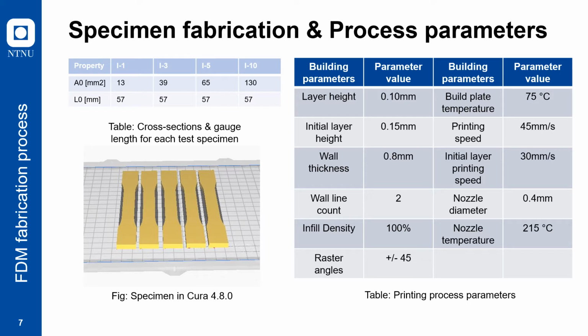Okay, so these are the fabrication parameters and the process parameters here. As I mentioned earlier, we have 4 different thicknesses for the specimen, and these are the cross-sectional area and the gauge length for each specimen. And these are the process parameters we have used to fabricate those specimens. We have made some trials and errors to be able to fabricate those, with 100% infill density and a relatively smaller layer height of 0.1 to be able to get a good quality specimen. So these are the parameters we have used.